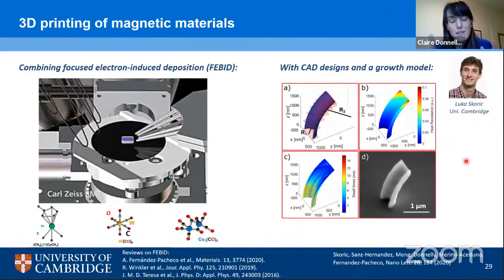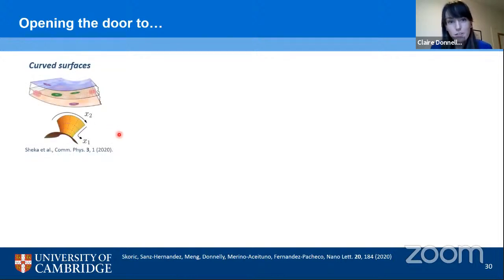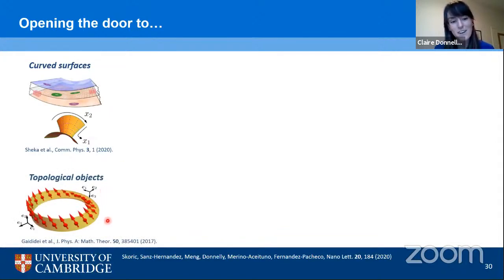So as you can imagine, these new 3D printing capabilities are incredibly exciting when it comes to 3D nanomagnetism, specifically because we can pattern it with this high purity cobalt. And what we went on to do was to identify a few different areas in which this might be particularly useful as a first demonstration. Two main examples are as follows. First of all, the introduction of curvature into a system or into a magnetic thin film. Now, it's been shown by theorists in the last few years, including Denis Sheka, that the introduction of curvature actually leads to emergent magnetic properties, such as emergent magnetic anisotropies and magnetochirality effects. In addition, when we go to 3D, we also have the possibility to go to new topologies, such as our Mobius strip here.